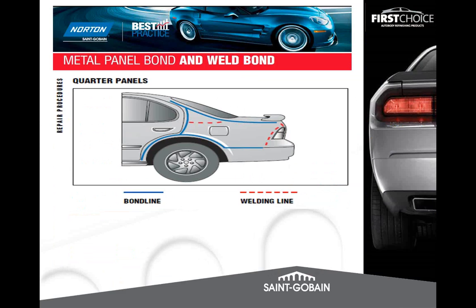So there are certain crumple zones that they put into the vehicle that they want specifically welded, the taillight being one of them, and also where the new panel meets the old panel. They want these areas to physically break so that those areas take the impact, take the energy, and it doesn't get transferred into the passengers of the vehicle. But you'll notice you can glue everywhere in between. So you can glue down the bottom of the panel, around the wheel well, all the way up and back towards the taillight. And the reason for that is because that's what the OEM is calling for. They want the weld to take the impact.